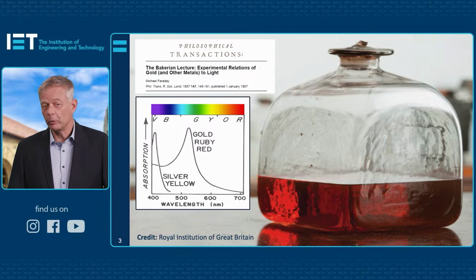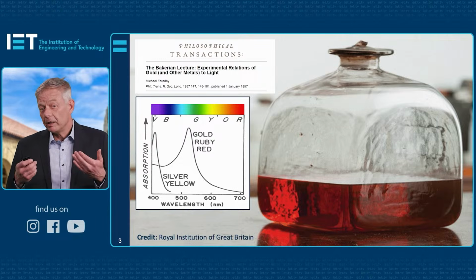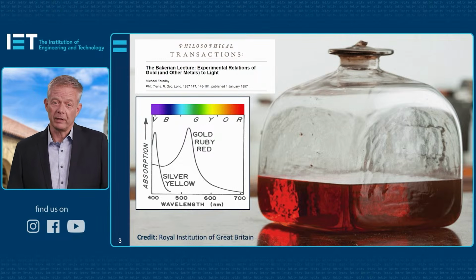If one would have done this with silver nanoparticles, then it turns out that the resonance would have shifted further to the ultraviolet part of the spectrum, and the color of this vial would have been yellow.